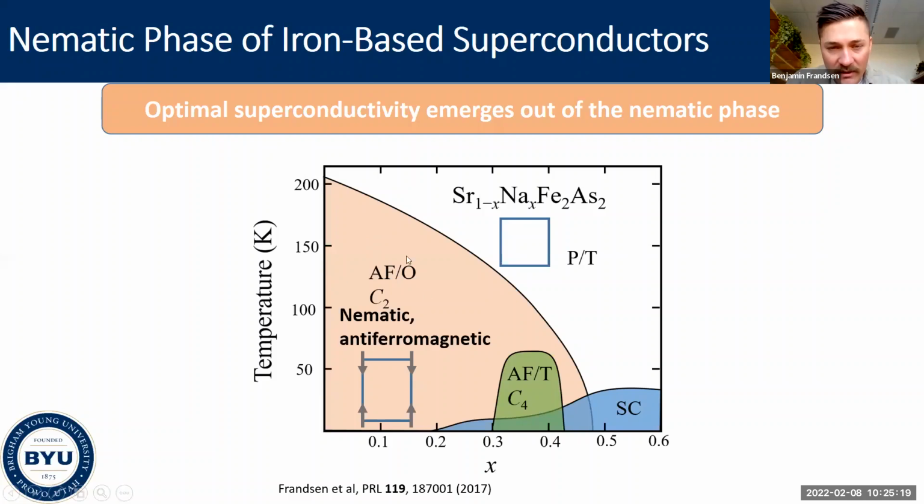Okay, so this phase right here, this is the nematic phase. It's antiferromagnetically ordered. It has that orthorhombic structural distortion. So we have this kind of rectangular structure with this spin order. Out here, this is a paramagnetic tetragonal phase. So this is non-nematic because the average structure is tetragonal. It maintains that square symmetry and there's no static magnetic order.